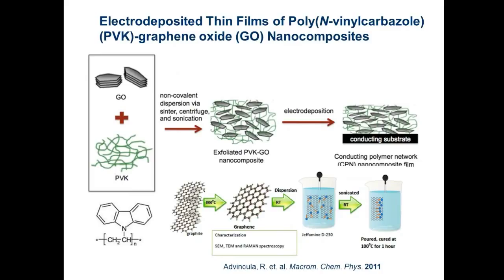Our first paper, back in 2011, involved taking the graphene oxide precursor and complexing it with a polymer called polyvinyl carbazole, PVK. The structure of PVK has a carbazole ring which complexes through pi stacking or pi-to-pi interaction with the graphene, dispersing it very well, such that we can make gels, make solutions, and electrodeposit the PVK-graphene oxide complex to form thin films.